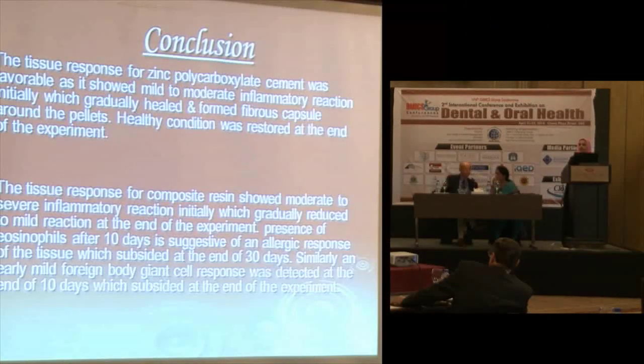Then the conclusion we came to was that the tissue response for zinc polycarboxylate cement was favorable, as it showed a mild to moderate inflammatory reaction initially, which gradually healed and formed a fibrous capsule around the pellets. Healthy condition was restored at the end of the experiment.